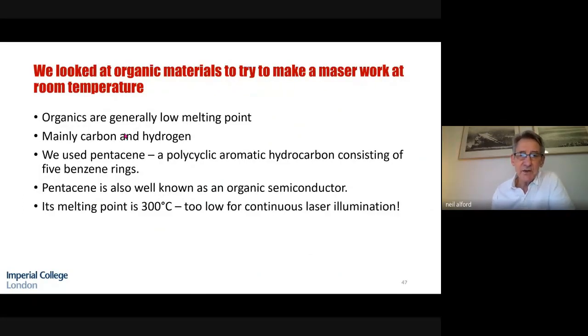Now, organics generally have a very low melting point, being mainly carbon and hydrogen, and we used pentacene, which is a polycyclic aromatic hydrocarbon with 5 benzene rings. It's also pretty well known as an organic semiconductor. It does have a slight problem. The melting point's only about 300 Celsius, so we can't illuminate it with a laser for very long.